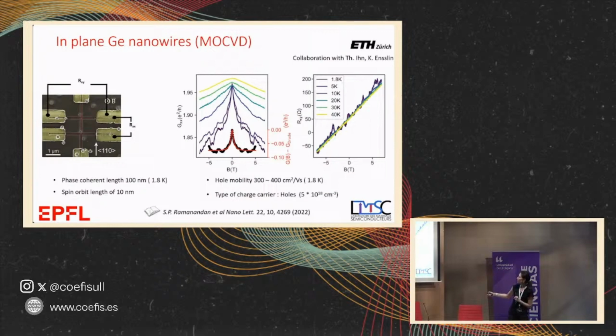This measurement here that you see is the conductance as a function of magnetic field. And you see, as we lower the temperature, we have a peak. And we also see a lot of oscillations. These oscillations are perfectly reproducible. And they are not noise, because they're perfectly distributed.